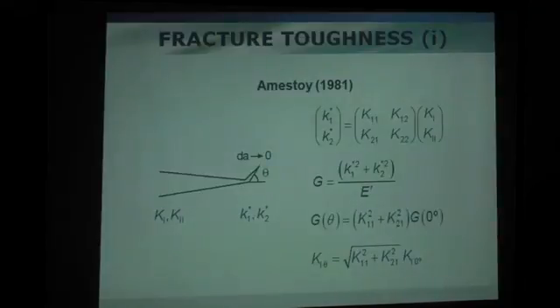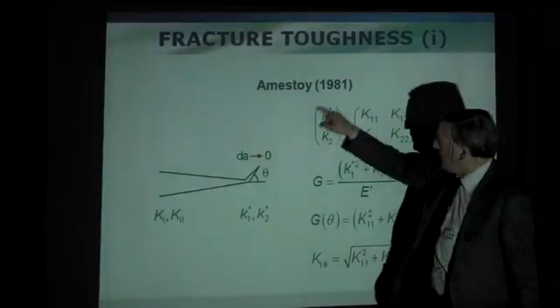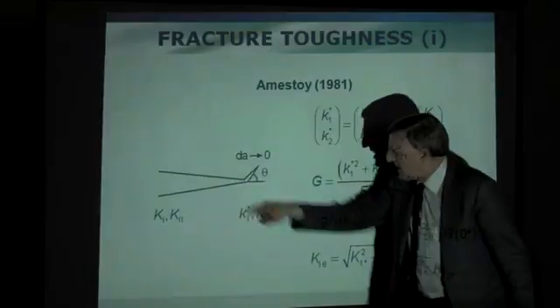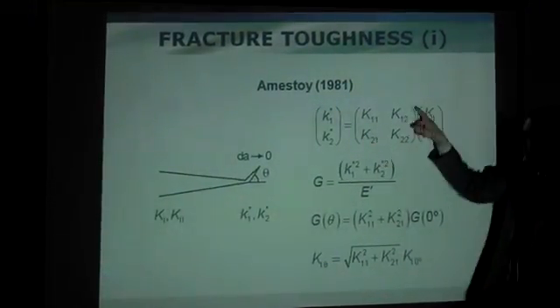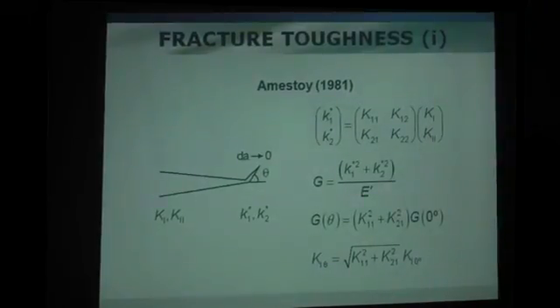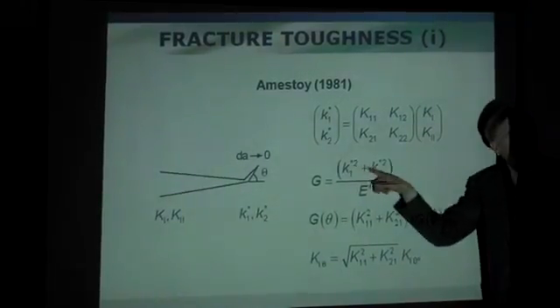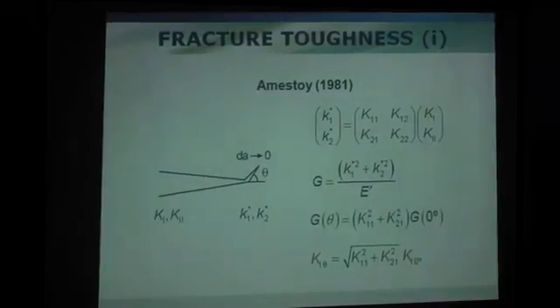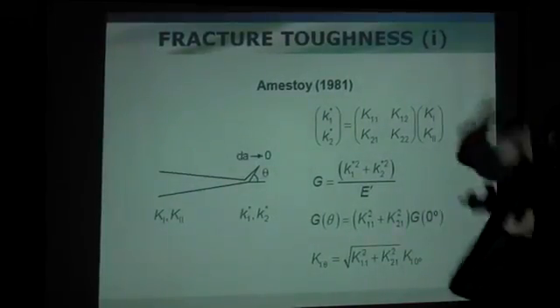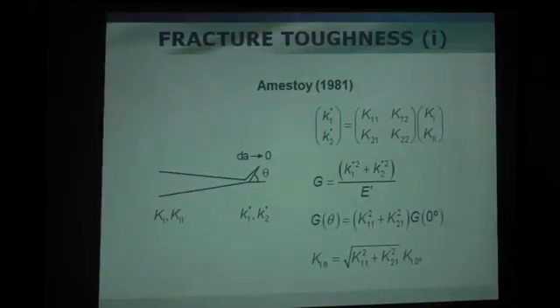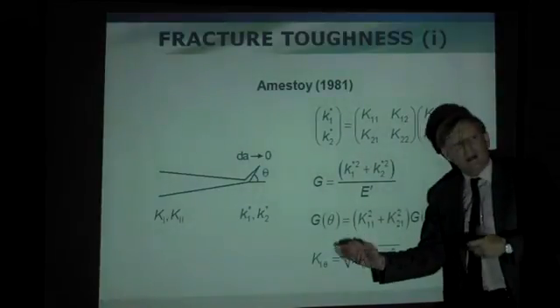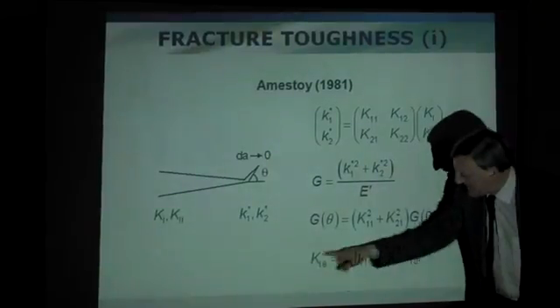And now we use the mathematical equations of the French school from a long time ago, Amestoy and others, I think. We use the local crack tip field, the local stress intensity factors, minor k1 and k2, with a matrix as a function of the global, in the fracture mechanics sense, K1 and K2. We define the energy release rate as a function of the local k1 and k2, and with this we have a directional J, a directional energy release rate, and on the opposite side we can retake the concept, theoretical or mathematical, not physical, of fracture toughness or pseudo toughness, or critical stress intensity factor, with directional properties.